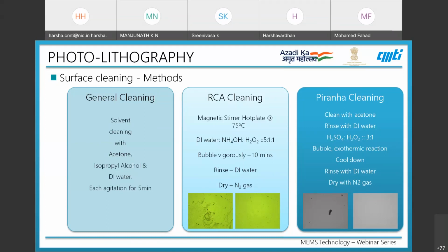As said before, the left-hand side image shows a sample which has some particulate content before the Piranha cleaning, and the right-hand side image shows that there is no particulate present at the same position on the same sample after Piranha cleaning.